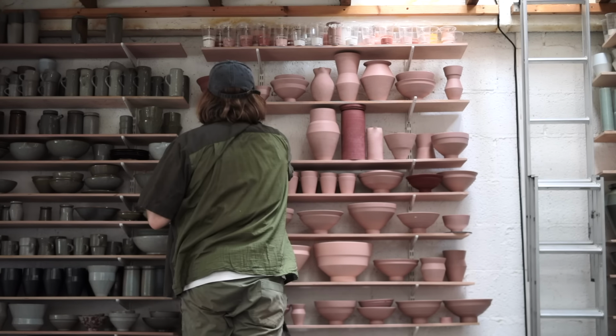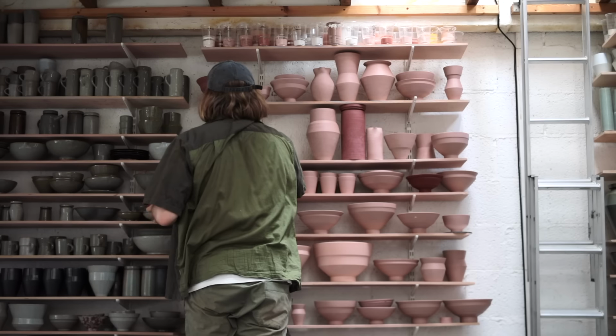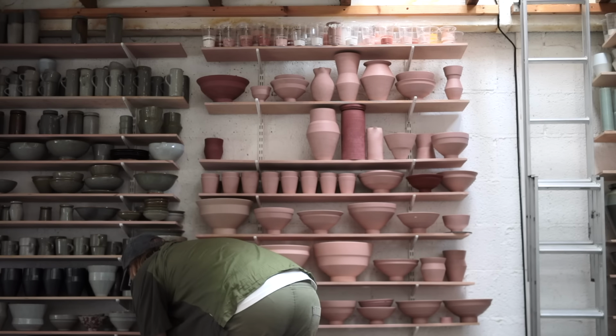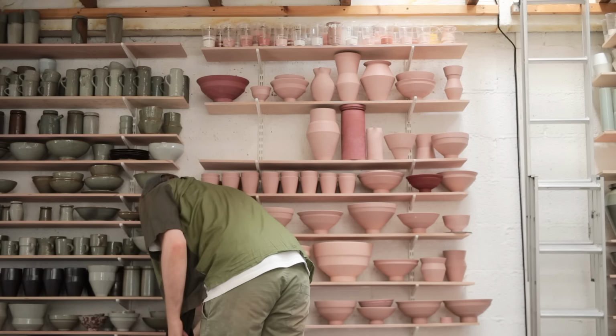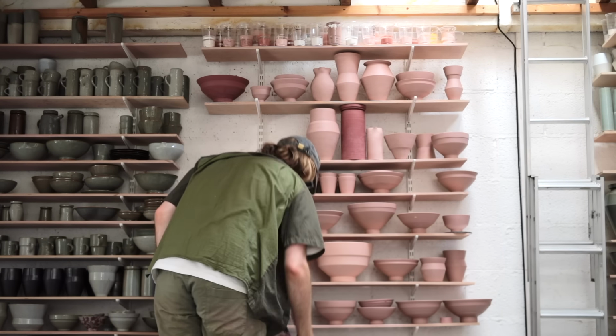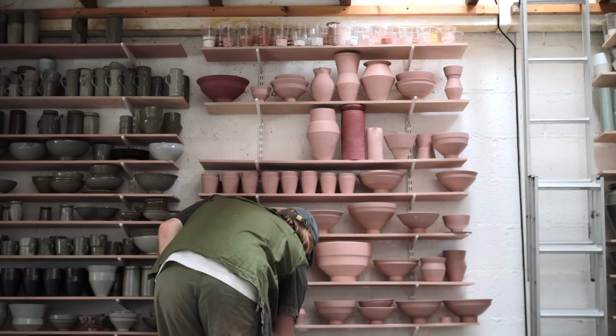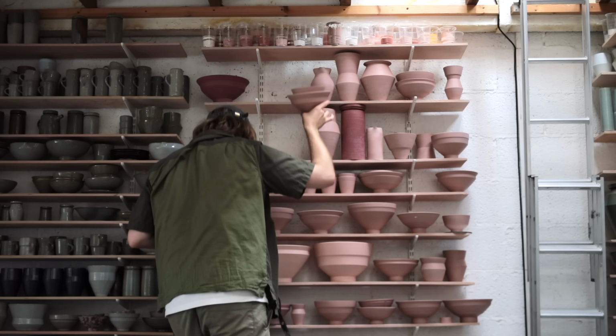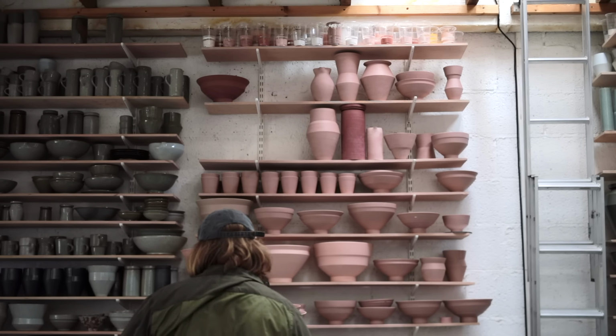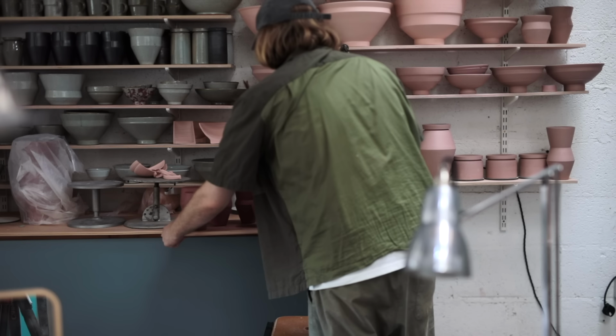It's now a couple of weeks later, and the vases are now completely bone dry, meaning there's practically no moisture left inside them, save for a tiny amount that's still chemically bonded that will be driven away during the subsequent firings. At this stage, the pots are at their most fragile, and simply picking one up incorrectly can cause the pot to crack or the entire piece to shatter. So how pots are picked up and held and are placed inside the kiln at this point is an entire skill in itself.